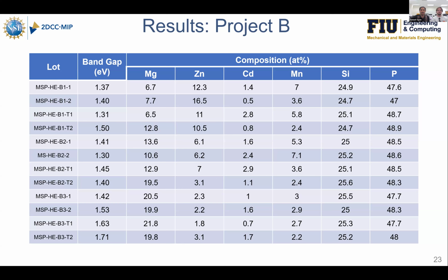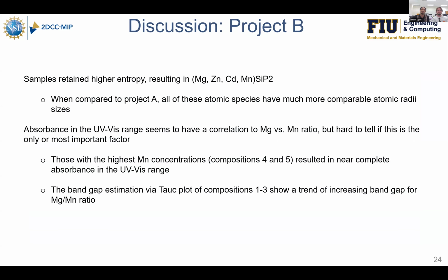So here we see that there's not as much of a difference with respect to the previous numbers. One reason we think these synthesized a lot better is that, first, there are already parent compounds synthesized for these, as we mentioned: the magnesium silicon phosphide, the zinc silicon phosphide, and the manganese silicon phosphide.